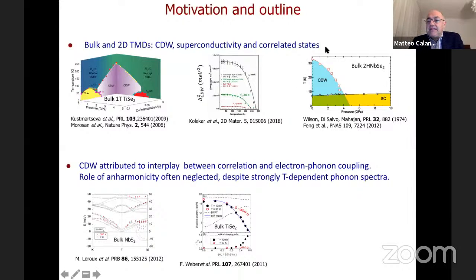Another classical example of competition between charge density wave and superconductivity is bulk 2H niobium diselenide, where if you are at zero pressure, for example, first you have a metallic state and a charge density wave state, still metallic, that at very low pressure and very low temperature coexist with superconductivity. Now, this system was the first where charge density waves were actually seen, 2H niobium diselenide, in 3 dimensions or 2 dimensions.